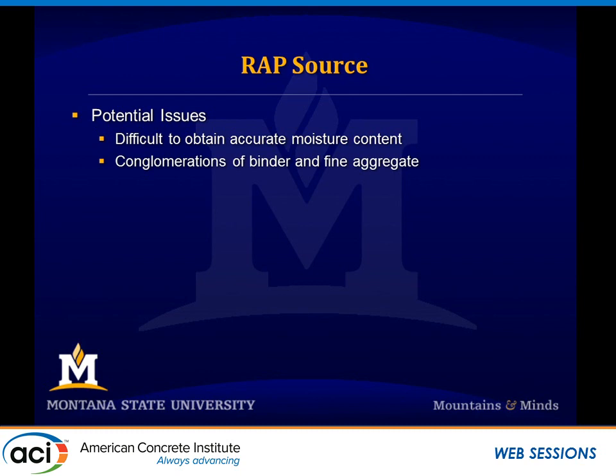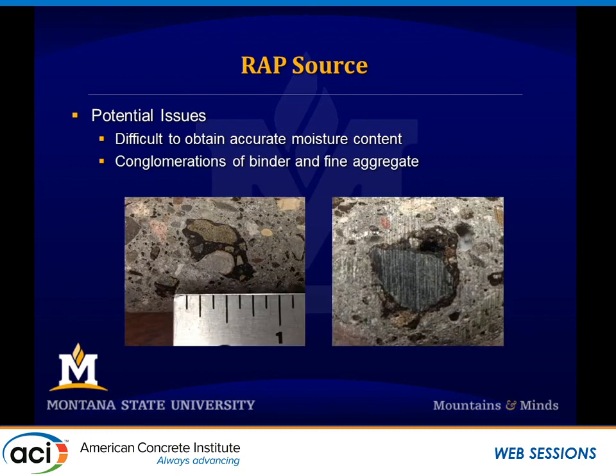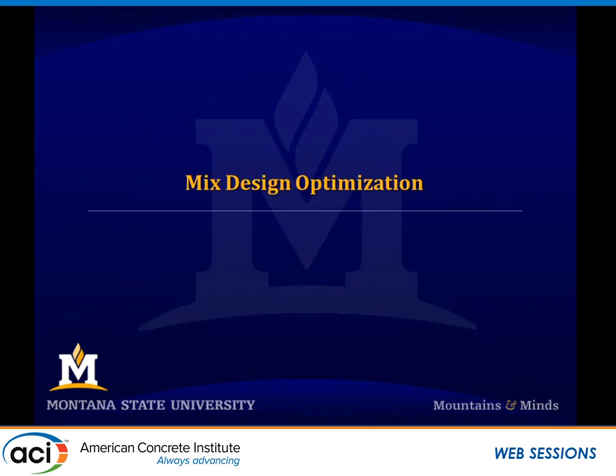The other issue was these conglomerations of binder and fine aggregate. And so here's some pictures of some cores that we took afterwards, and you can see that both of these things would be considered a coarse aggregate, right around a 3/4 of an inch, but you can see that it's not really a coarse aggregate. It's really a clump of tar with some fine aggregates inside of it. And then we believe this played into our decrease in performance, which we're going to get into in a little bit, having these conglomerations in here. But we wanted to stick with our minimal processing technique.